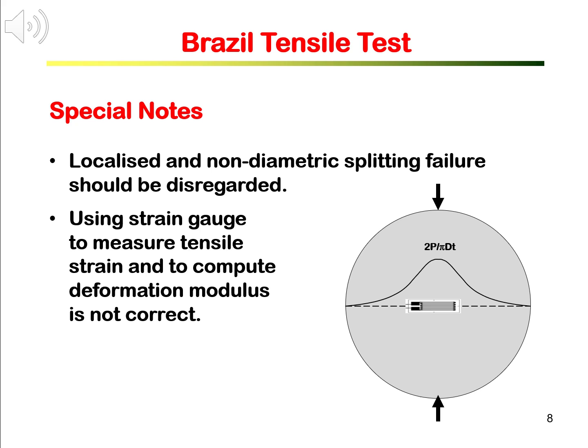The specimen should fail by splitting along the diameter across the loading points. If failure is localized failure, not by splitting the disc along the diameter, then the test is not valid. The data from this test should not be used for strength calculation.